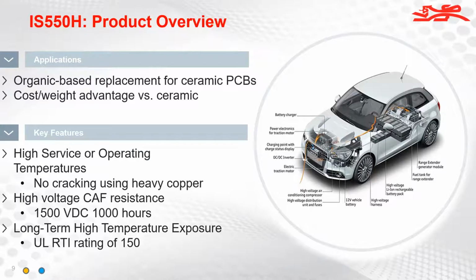And so one of the things that also is a concern with these types of products is, what's the highest temperature they can operate at? Well, you typically are limited to about 150 degrees C with some of the newer materials, but operating temperatures, as I mentioned earlier, are going to be higher than that on a cyclic basis. So this material has been tested, and we'll go through some of that in a little bit, at much higher temperatures than 150 MOT or RTI rating.